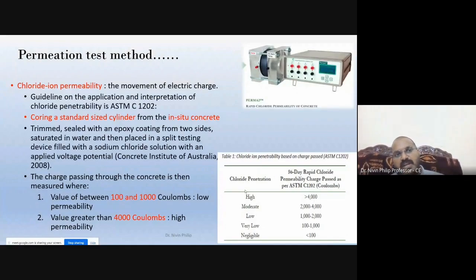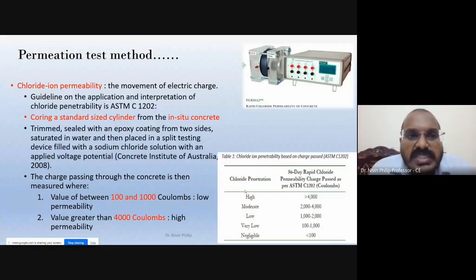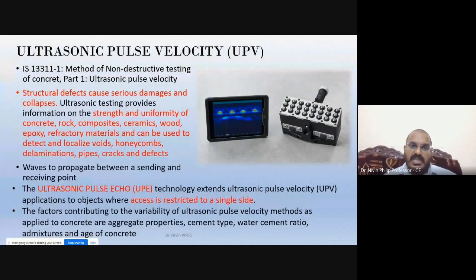And another is ultrasonic pulse velocity. It is another technique used to measure the uniformity and damage of concrete: interior damage, any honeycomb, delamination. So UPV is the initial technique that was developed. Now the most modern technique we call ultrasonic pulse echo, which is a little bit modified from the UPV test.